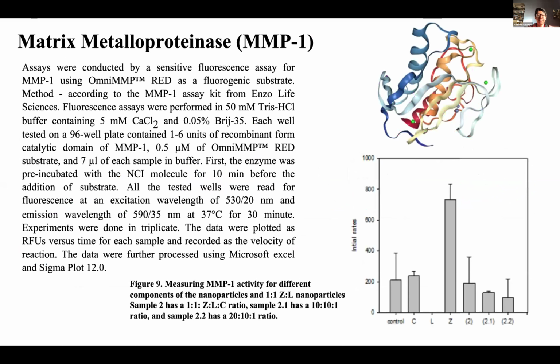And then we assayed them for their activity on MMP1, which is a collagenase. Collagenases break down collagen, and it causes wrinkles if it's too active, which is why we tested it on our nanoparticles. You can see that some of them upregulated and some of them downregulated MMP1. The ones that were upregulating it, you would think that's not desirable because it causes wrinkles, but on this occasion, it could be desirable for something like treating wounds so that you don't develop scar tissue. And then downregulating it, as I mentioned before, is good for preventing wrinkles, which means that we could use our nanoparticles for some kind of cosmetic purpose.